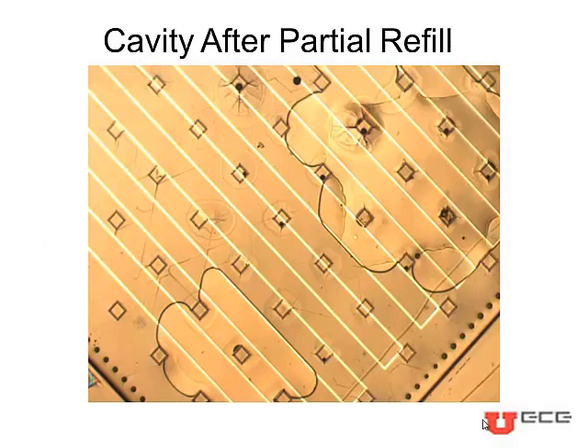This photograph shows the partial refill of the cavity with BHF when the sample was quickly pulled out of the bath, showing the presence of bubbles. These bubbles can be removed if the sample is immersed in the bath for about 2 hours. After the samples are pulled out of the bath, they are flash frozen and air dried.